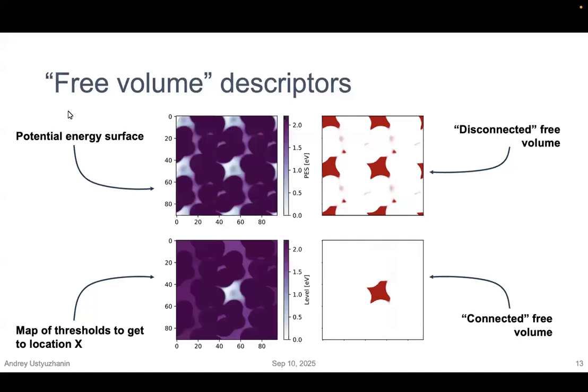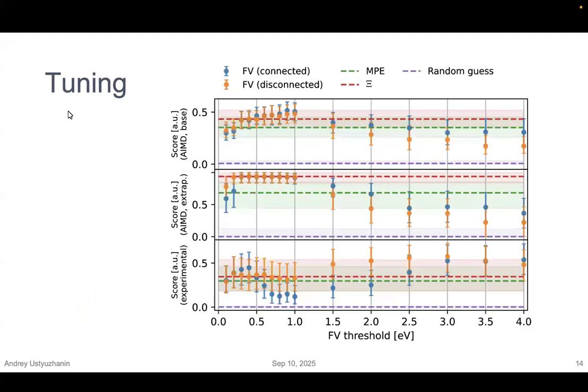So here is a more illustration how this free volume descriptor looks like. So we have this potential energy surface, and we apply some kind of threshold, removing everything below threshold. That gives us some free volume, and we can compute this free volume relative to the volume of the lattice. Or we can compute connected free volume. So there are some variations of what we could do.